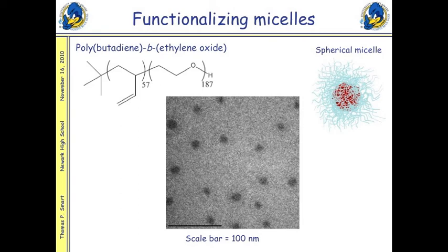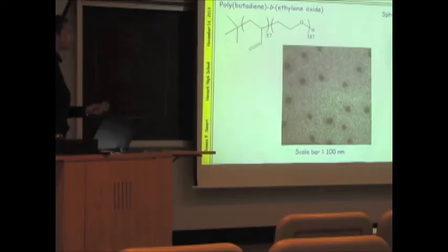And so everything is more or less the same length. And then you can add the next one, and then the chains grow on from that. And by the ratio between the initiator that you use and the monomer units you use, you can control how long each block is.